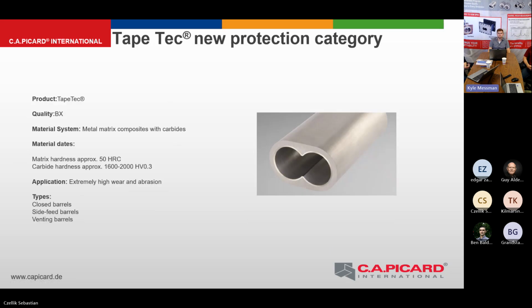So BX was a development made by Picard, and it's called TapeTec because that was a project name. And here we have a metal matrix with carbides. So the matrix has a hardness of about 50 HRC, and the carbide cannot be measured in HRC anymore. So the 1600 to 2000 HV, that should be around 75 HRC. And there you get a very high wear resistance paired with abrasion resistance.